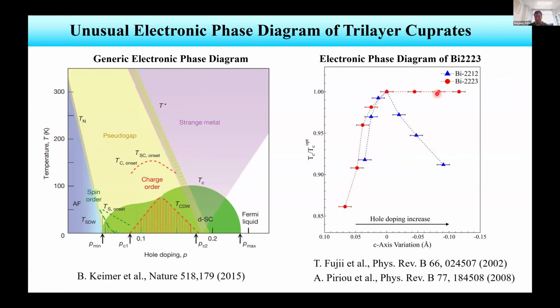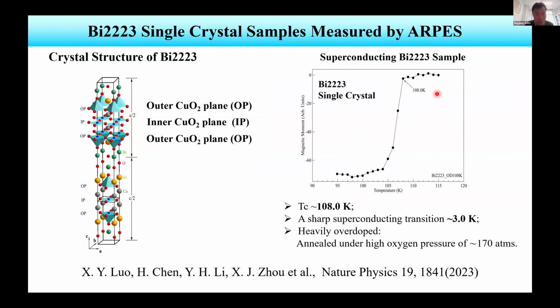So why this? Okay. So we performed laser ARPES on this bismuth 2223 system, and before that we made a new sample. In bismuth 2223, in one structure unit you have three CuO2 planes. We call the central one the inner plane and the two outer ones the outer planes, so OP and IP. That's what I'm going to use later in the talk. For this bismuth 2223 sample, we annealed it at a very high oxygen pressure of 170 atmospheres to make it heavily overdoped. But TC is still high, about 108 Kelvin. It's a very high TC, but it's heavily overdoped.